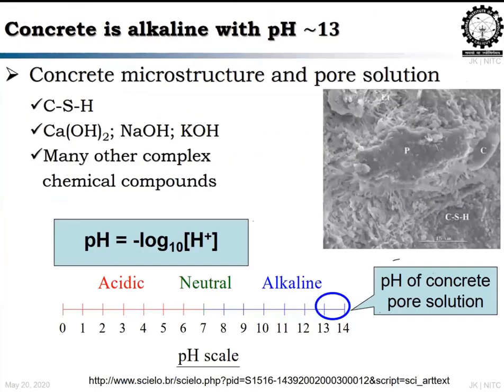Why does the steel corrode? Okay. Usually the concrete is rich in high pH, around 13 to 14, because of the presence of a lot of alkalis. That is well known. But how does it reduce, or why does the steel corrode? In high pH, the steel will not corrode, that is well known again. It needs an acidic environment to initiate corrosion. We need a pH of less than 10 to initiate corrosion. Okay. But how is the environment favorable for the steel to corrode?